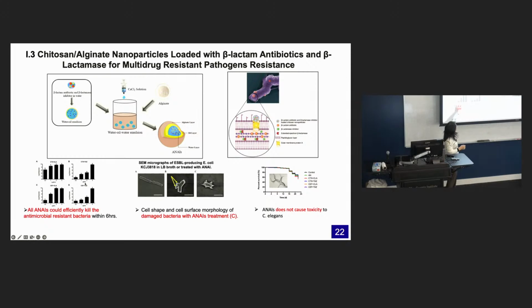So we successfully encapsulated two antibiotics and two inhibitors. This data shows they can efficiently kill the antimicrobial-resistant bacteria within 6 hours. This SEM picture shows that the bacterial cells are damaged, and this work shows our material doesn't cause toxicity, using C. elegans as an example. There are several papers based on that.